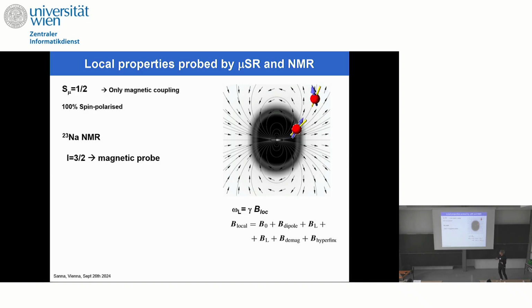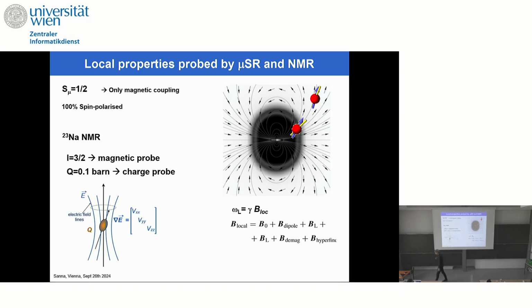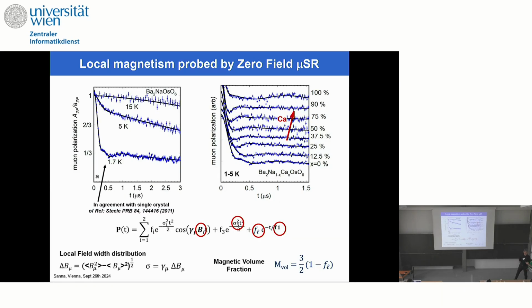By implanting muons, spin 1/2, mainly coupled to magnetic degrees of freedom, and by doing sodium NMR, which is coupled both to magnetic properties and to charge-related properties. Let's have a look at the results, and these are the μSR data. This is the sodium compound, a powder sample, but it is in very good agreement with the single crystal results on the sodium compound published in 2011. So the powder behaves in the same way.